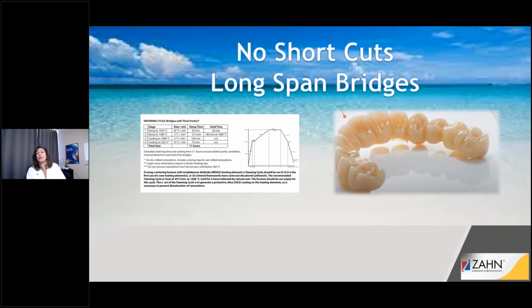When we are talking about long span bridges, there really are no shortcuts. We do not ever want to use a 4-hour program or even the 7-hour program. You need to give these restorations the time that they need in the furnace so that they're not warping, so that the restoration is getting the accurate amount of heat all the way through those thick parts of the bridge. Anytime I've seen anyone do shortcuts on a large span bridge, it doesn't turn out so well. So I strongly recommend, if you're doing something like an all-on-4, absolutely use your 11-hour program.